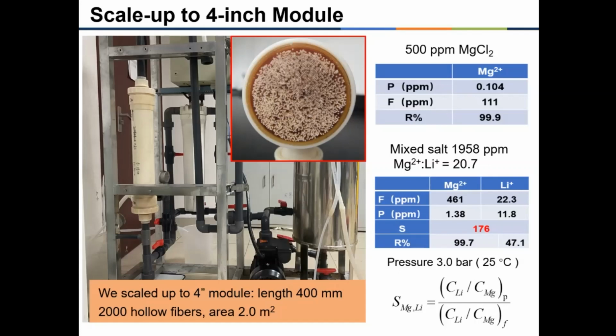A 4-inch module was fabricated and tested in the laboratory. The module length is 400 mm with 2000 hollow fibers. Surface area is 2 square meters. The rejection of magnesium was 99.9%. The separation factor of magnesium-lithium is as high as 176.